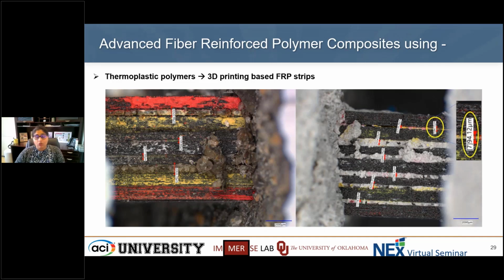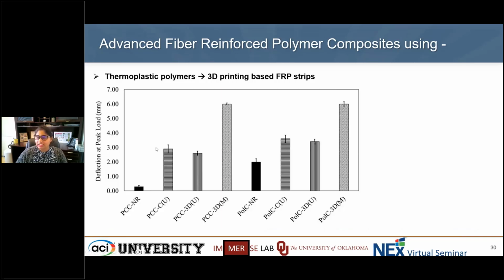One of these concretes here is Portland cement concrete, and the other here is polymer concrete. In the polymer concrete, we have used methyl methacrylate based polymers, and we've seen that this polymer concrete has the potential to seep into the gaps between these FRP composites, as low as 94 micron, you can see. And that has helped a very important behavior, which is deflection at peak load. You see that for a Portland cement concrete with this 3D printed multi-directional reinforcement, when compared to unidirectional that is 3D printed and a conventional unidirectional, the deflection is almost 100% increase.